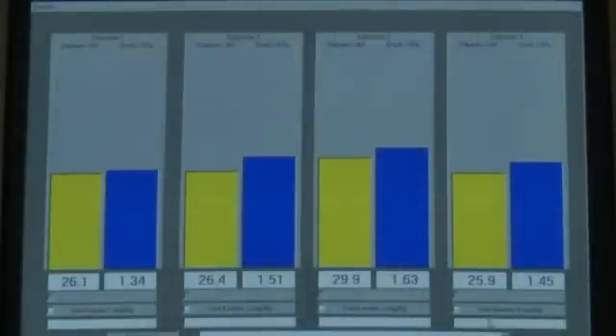requires that spot checks are made ensuring that the bursting volume of a condom, after an artificial aging process, respectively until the actual expiration date, must amount to at least 18 litres. All MAPA quality condoms exceed this threshold by far.